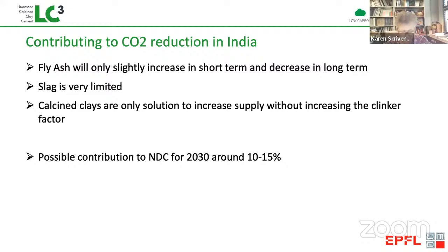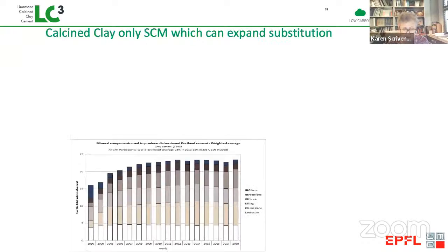And I think someone is going to talk more about this, but the kind of contribution we can imagine to the nationally determined contribution for 2030 is around 10 to 15%, which is really very significant. On a worldwide level, what we see is the current average level of clinker substitution today is only around 20%. And this is due to the limited availability of slag and fly ash.